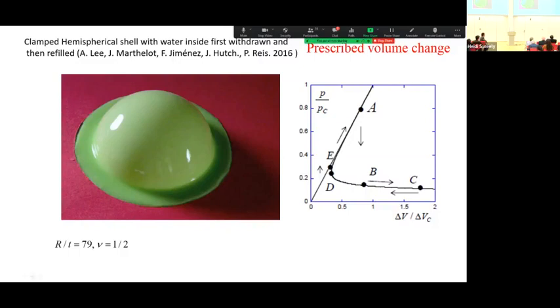And so what we're going to see is we're going to go up to A. That's where it buckles. So this was a nearly perfect shell. Buckles at 80% of the classical. Because the volume is prescribed, it snaps at the same volume down to B. And then, I mentioned this earlier, then they continue removing water and it goes out along this stable post-buckling curve, and that's down below 20% of the load carrying capacity of the perfect shell. And they go way out here, by the way, and then they bring it back and it gets back to D, point D, and then it snaps back to the perfect state. So let's do that one more time, seeing that.